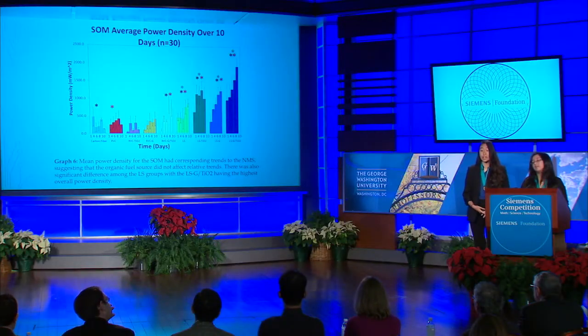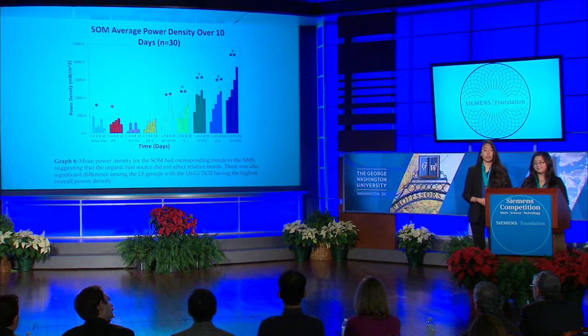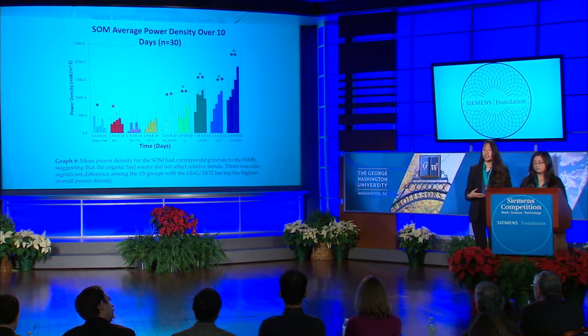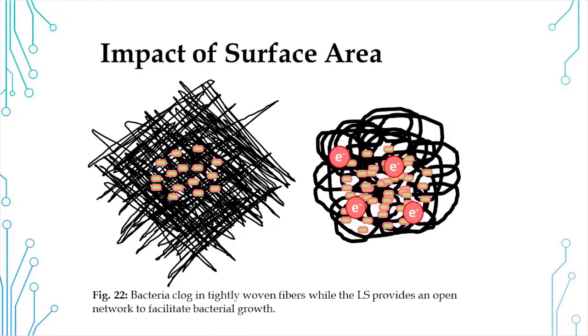For the simulated organic matter system power density graph, the trends are similar to the natural marine sediment, indicating that the organic fuel source doesn't affect overall trends. In an MFC, the porous material allows for biofilm growth and a continuous flow of electrons. This is supplemented by the composite. Overall, in the loofah sponge composite, its open macroporous structure and its hybrid surface coating can synergistically enhance biocompatibility, electrical conductivity, and extracellular electron transfer efficiency.